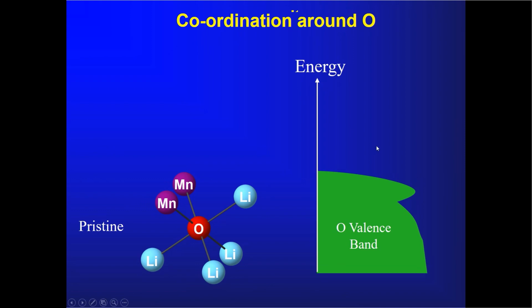So to get a sense of what is largely contributing to the voltage loss on that cycle, when you move from the nice plateau at high voltage to the curved discharge at much lower voltage, to get a sense of, in terms of the electronic structure, what is giving rise to that big loss of energy, we can look at this. It's of course captured in the DFT, but just to get a sort of chemist's view, if you like, of the main elements of that energy change at an electronic structure level. I think this is a useful picture.